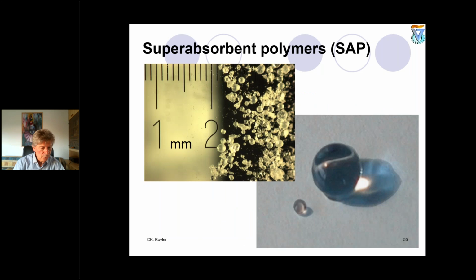This is another class of internal curing agents, which is called SAP, or superabsorbent polymer. You can see what the particles of this superabsorbent polymer look like. This is one of the examples. When it absorbs water, the dimensions increase dramatically. Usually, from a chemical point of view, this superabsorbent polymer is a hydrogel. And this hydrogel is mainly containing water. So the density of the particles of superabsorbent polymers is like water. So most of the volume is occupied by water.